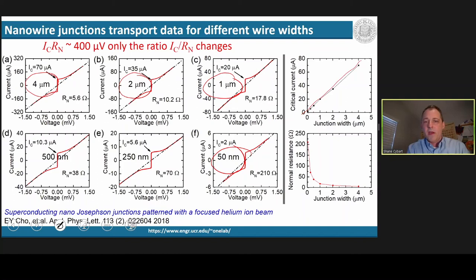Furthermore, the normal state resistance is going up as we expect as well. And this gives us a way now to tune the different amounts that we have of IC and RN to optimize the squid for noise and performance.